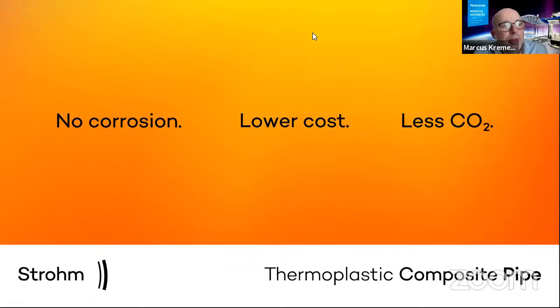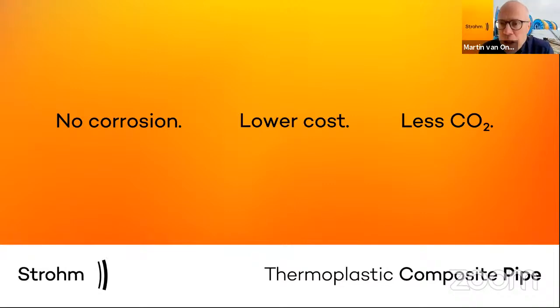Maybe you can give a little bit of an impression. What kind of pressure ratings are we talking about? When we look at composites, we can do pretty much anything, right? We can go to the highest pressures possible. Today we are up to 860 bar for small pipes. For larger pipes, where we go to 6-inch or even bigger, 7-inch, we can achieve 10,000 psi, which is 689 bar. So that's the internal pressure.